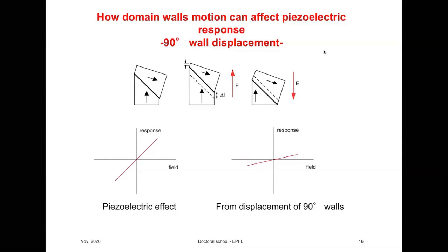And we can make this very general statement: ferroelastic domain walls will contribute to piezoelectricity, while purely ferroelectric domain walls, which are not also ferroelastic, will not contribute to the piezoelectric effect. So I will stop here and we will continue on the same topic.